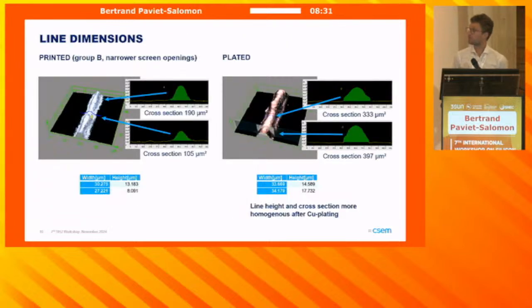Here we have a couple of pictures of how the line looks before and after plating. On the left, that's the seed grid. Here the cross-section is between 100 and 200 square micrometers. You can also notice that across the line there is this typical inhomogeneity of the height, which is a result of the printing process. Conversely, on the right, after plating, first of all, the cross-section is increased up to 400 square micrometers. And second, the height is much more homogeneous across the finger due to the leveling effects provided by the plating process.